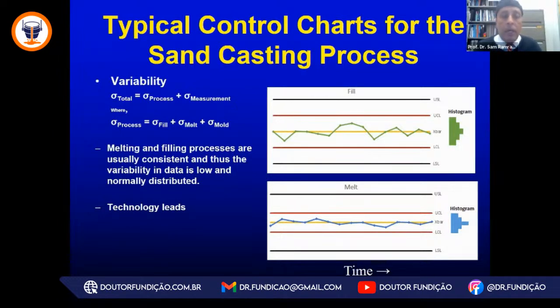Process variability is made up of the three important areas in foundries: the variability from filling, the variability from melting, and the variability that could come from molding. The melting and filling processes are usually consistent, as depicted on the right. These control chart slides show that the consistency offers low variability in the data, and that it is normally distributed in such a way that we could predict what's going to happen next in fill or in melt technology.